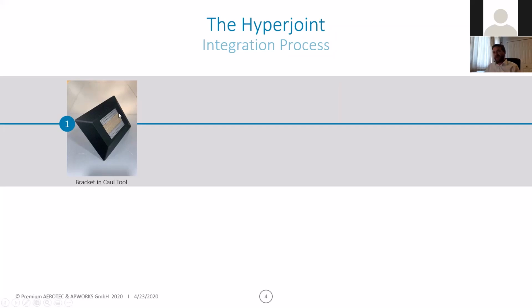In this case, the caul tool is integrating the bracket fitting, so you're slotting it into that tool. And that's helping to maintain the profile of the laminate as you go away from the interface. Otherwise, as we discovered in the early days, you can get a wrinkle in the laminate. And of course, that's defeating the object to some extent, because one of the big advantages of the joint is getting rid of the effect of drilling out a bunch of fibers which would otherwise be carrying load.